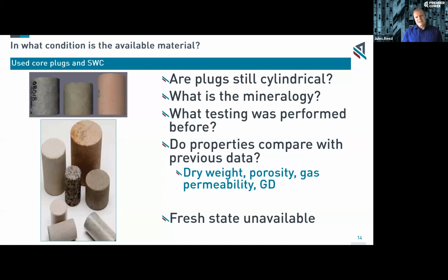We then also need to consider things like the mineralogy of the sample, because, together with the testing that has been performed, there are certain minerals that may have caused problems and may have caused changes to the sample and the sample properties. And one of those might be something like kaolinite, where the cleaning, the flooding, and then additional cleaning may weaken kaolinite booklets. You may then have induced fines migration. And so you might want to do testing for that before you start using the samples. Another mineral that you might want to think about is smectite. Of course, smectite is a swelling clay.